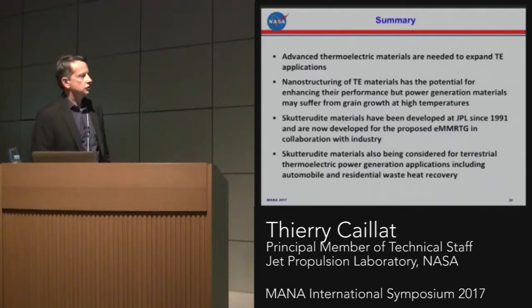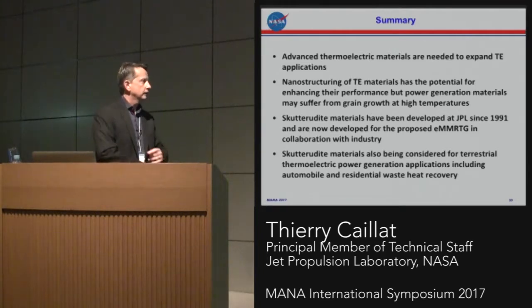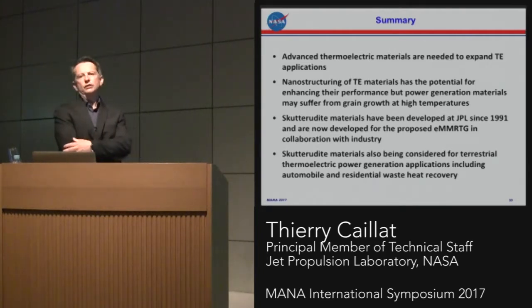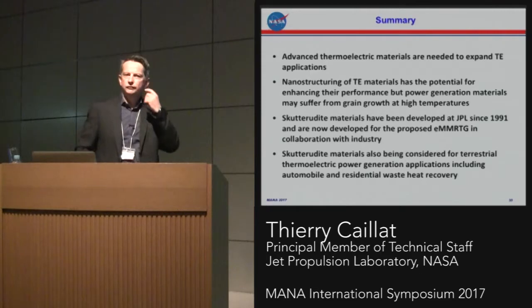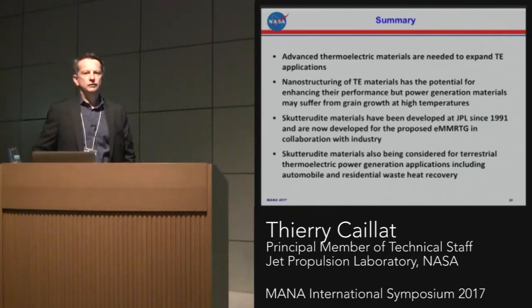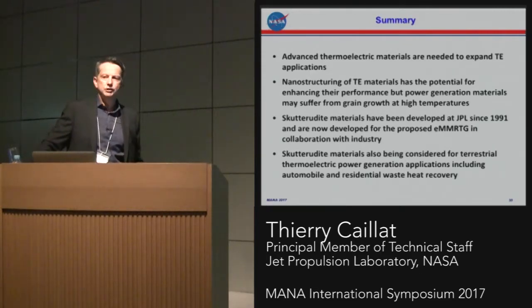The next slide goes through this, but I'm going to skip it in the interest of time and just wrap up. We're always on the lookout for advanced thermoelectric materials. This is a great deal for us in terms of improving the efficiency of the RTGs. This is really enabling for potentially a number of missions. Nanostructuring has its own challenges for our application because we're operating at high temperature. Unless you find a way to control the grain growth, that's potentially an issue.